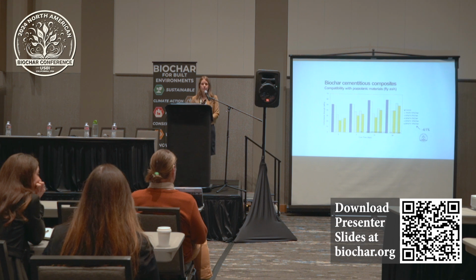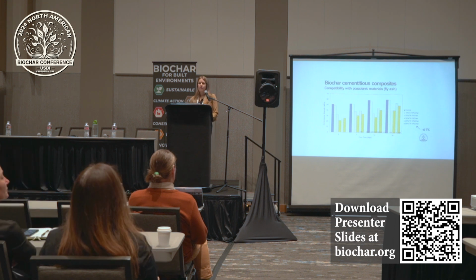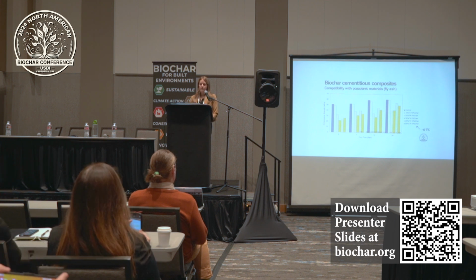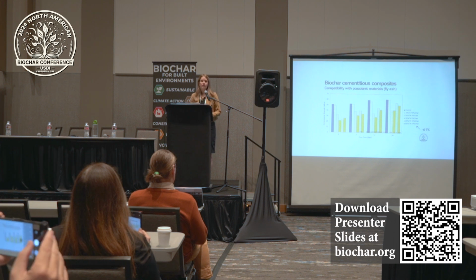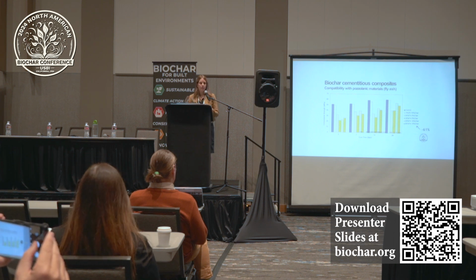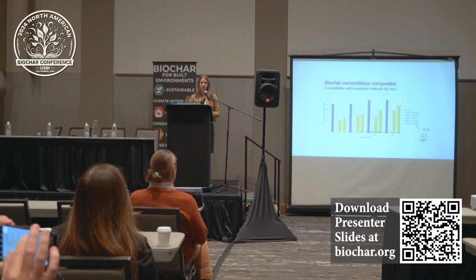So remember, that's one of those pozzolanic materials that we use in concrete, and it's very commonly used. So we want to make sure that it's compatible with some of these other solutions. And what we found is that the biochar is really useful for accelerating the strength gains in these composites.